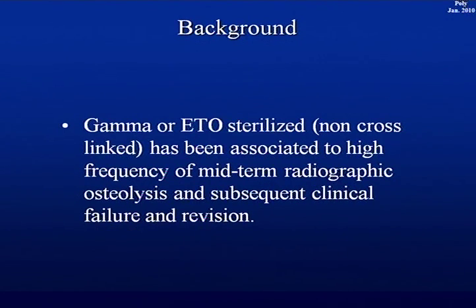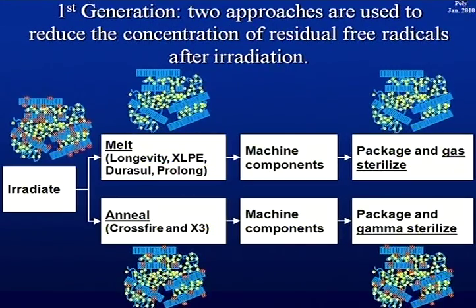The background for poly is gamma or ethylene oxide sterilized non-cross-linked poly, which was associated with a high frequency at midterm of radiographic osteolysis and subsequent clinical failure and revision. And this is then how the polyethylene was improved. You irradiate it to cross-link it to give more wear resistance. And then you can go either that route or that route.